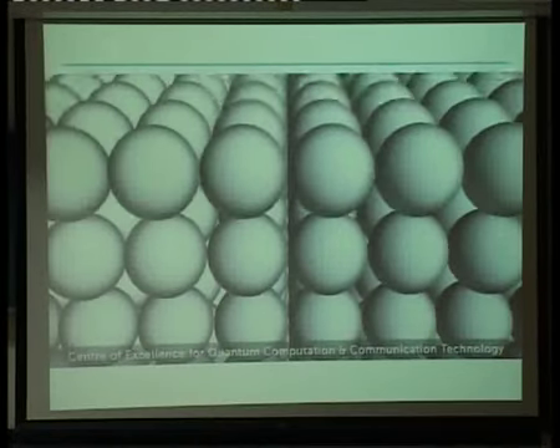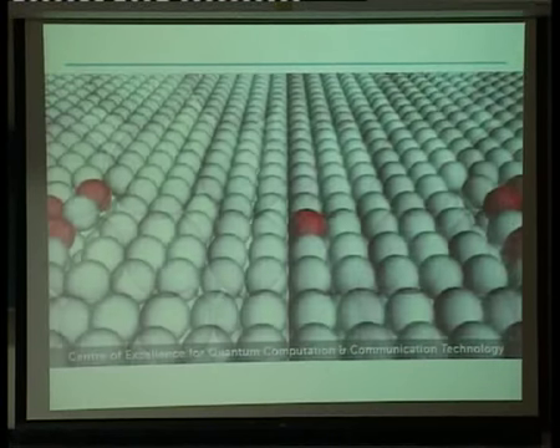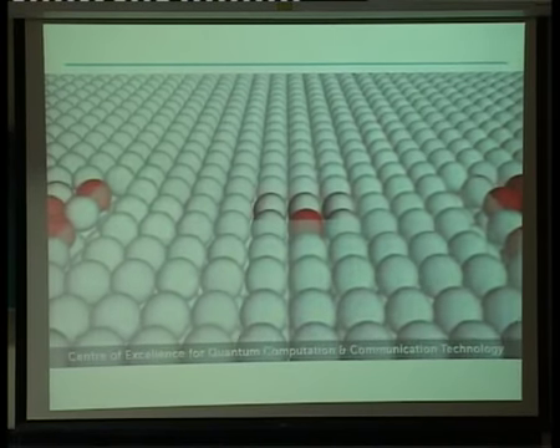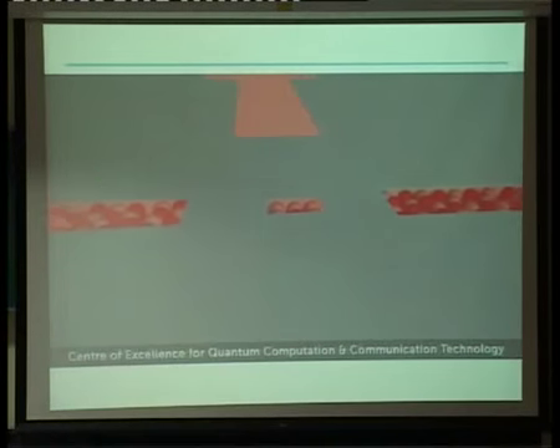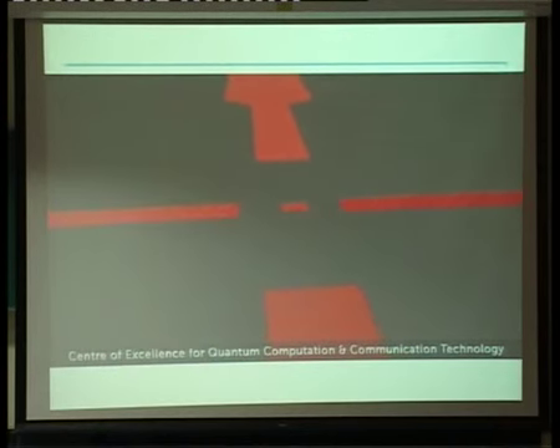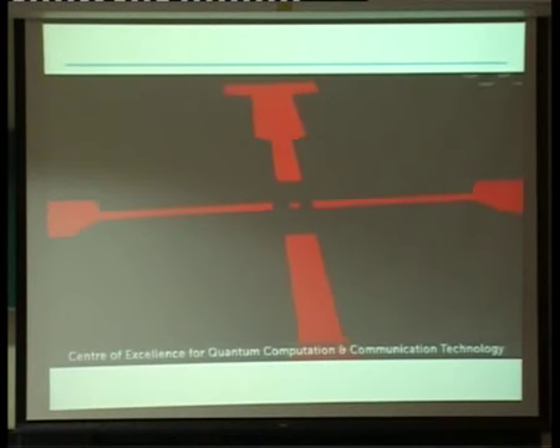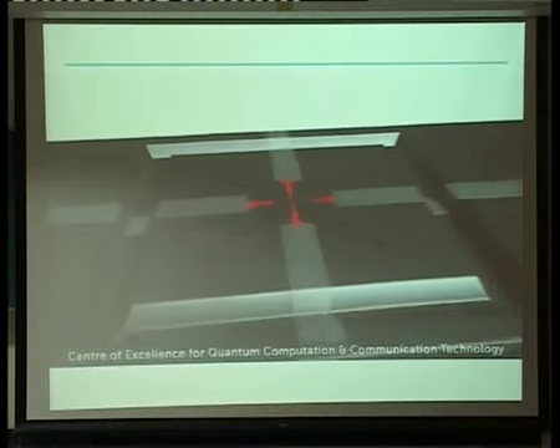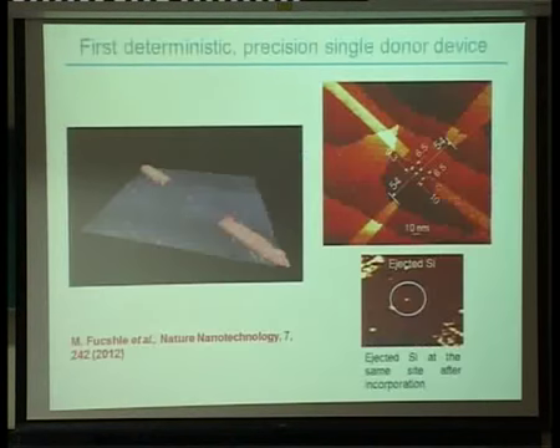But the critical part is when we open up that hole to put the single phosphorus in, as I mentioned before, we open up these lead states, and we saturation dose these at the same time. And once we zoom out, you'll see that those lead states are registered with respect to the registration markers on the surface, which we then use outside to put aluminium contacts down in a conventional clean room using EBL. So that's how we make the single donor.